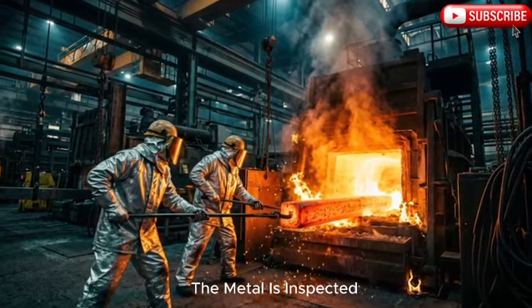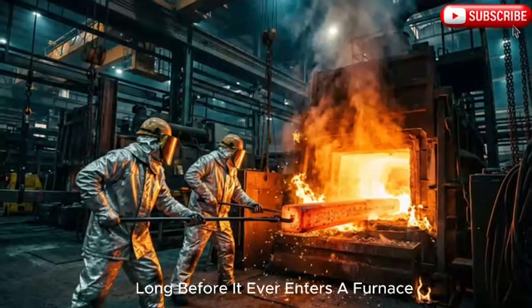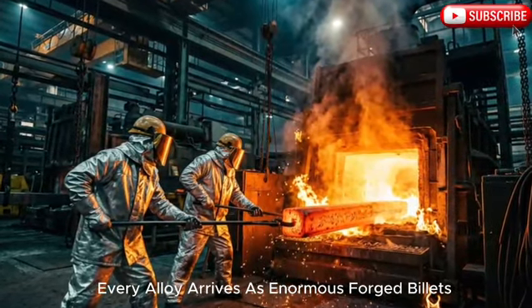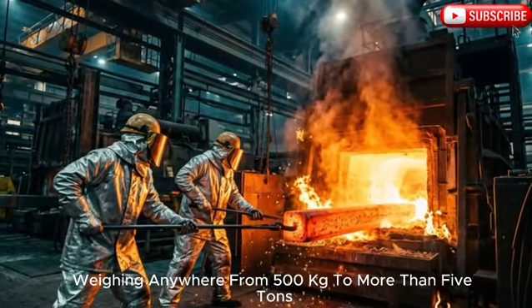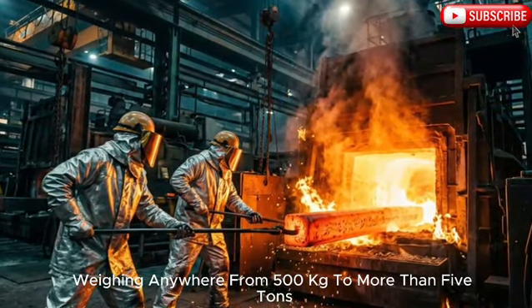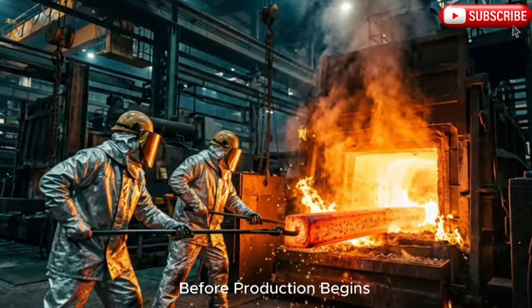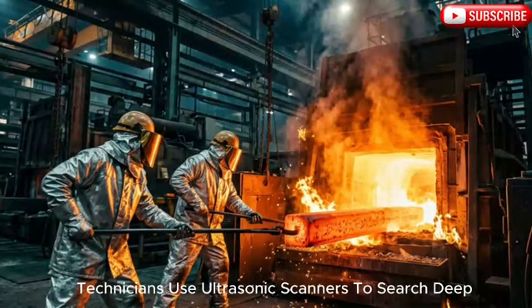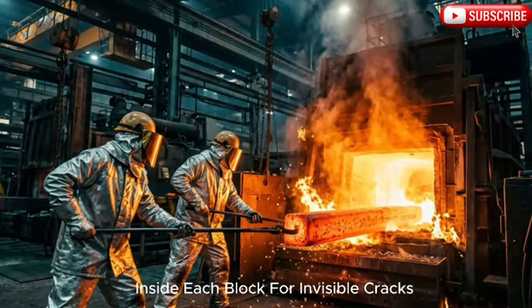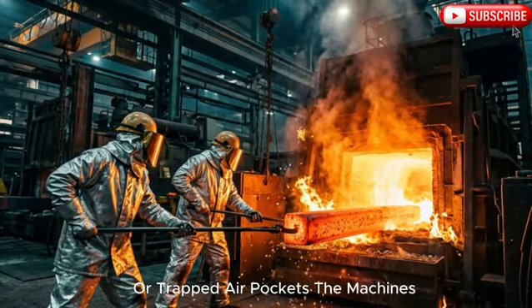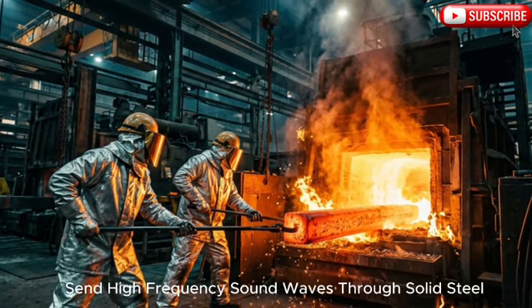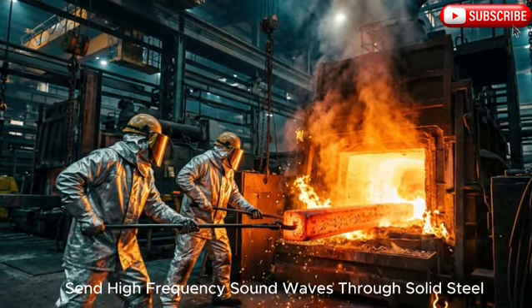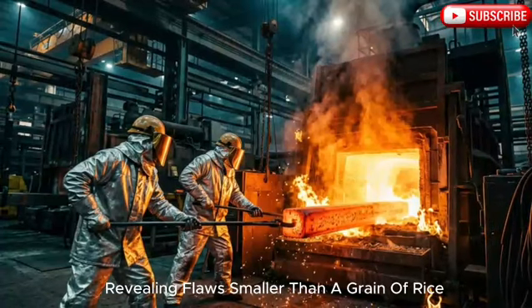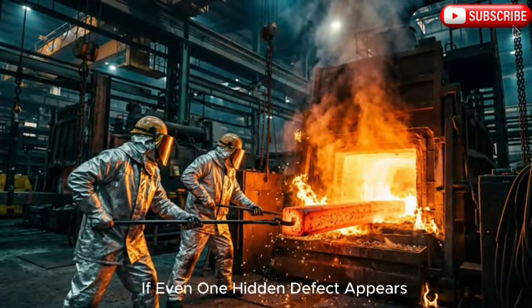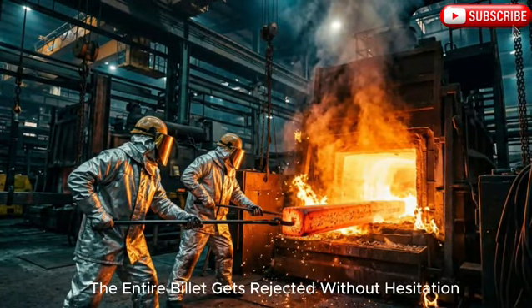The metal is inspected long before it ever enters a furnace. Every alloy arrives as enormous forged billets weighing anywhere from 500 kilograms to more than 5 tons. Before production begins, technicians use ultrasonic scanners to search deep inside each block for invisible cracks or trapped air pockets. The machines send high-frequency sound waves through solid steel, revealing flaws smaller than a grain of rice. If even one hidden defect appears, the entire billet gets rejected without hesitation.